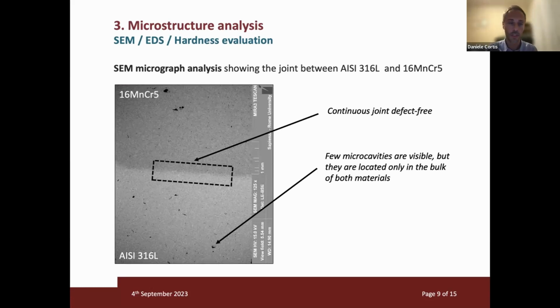It's very hard to reach 100% density, because you can reach it on a cube, a very simple geometry, but when you build a very complex component, it's also very difficult to analyze it. Only with tomography, for example computer tomography, you can see if there are defects in the components, but it's an issue that has to be studied and taken into account when you study the properties of an SLM component.